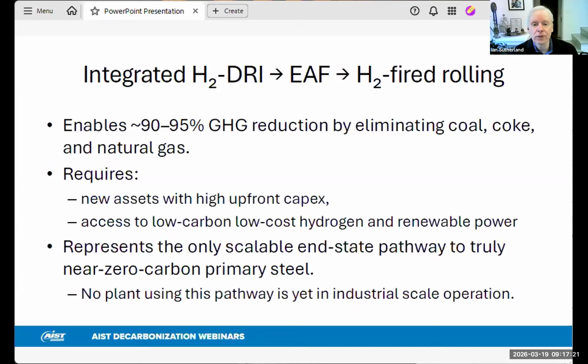So bringing these individual hydrogen use cases together into an integrated decarbonized iron and steelmaking process really suggests the following preferred pathway. Firstly, producing DRI with hydrogen as the reactant, then potentially using hydrogen in an EAF as a supplementary source of thermal energy, and then using hydrogen for thermal energy in rolling mill furnaces. And by following this pathway, there is the potential to reduce greenhouse gas emissions from the iron and steelmaking process by 90 to 95% compared to current conventional technologies.